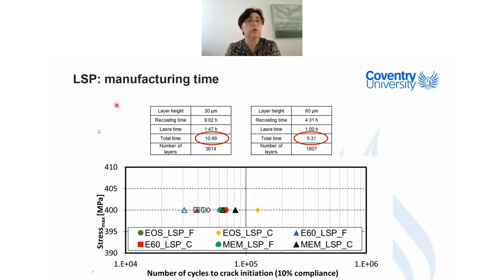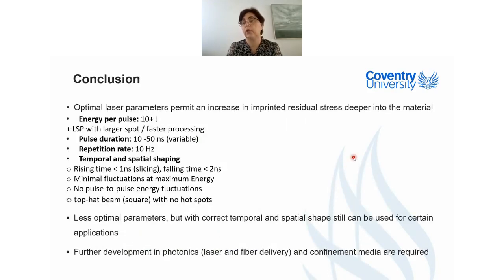After that, we started working also on titanium alloys in cooperation with Memphis University. And what you can see here, they were printing parts like that using two different methods, where one of them corresponds to a more optimized and another one to a less optimized process. The green is obviously representing the less optimized parts, and we peened those samples, and then we performed fatigue lifetime tests. And you can see that for all of these samples, we were able, depending on the load, to prolong the lifetime. For example, for a certain one, we were able to prolong lifetime up to 100%. So even for a less optimized process, it was possible to improve the performance.